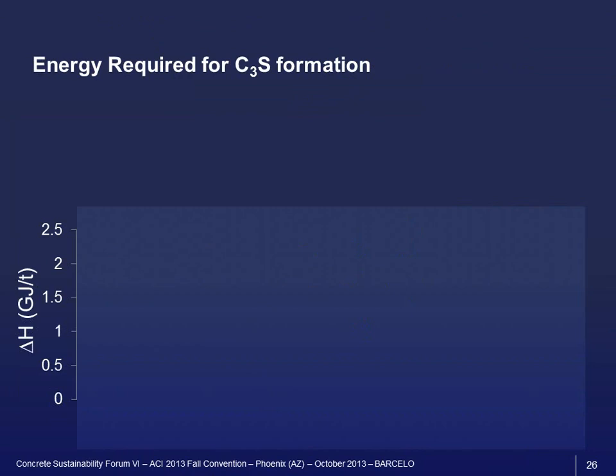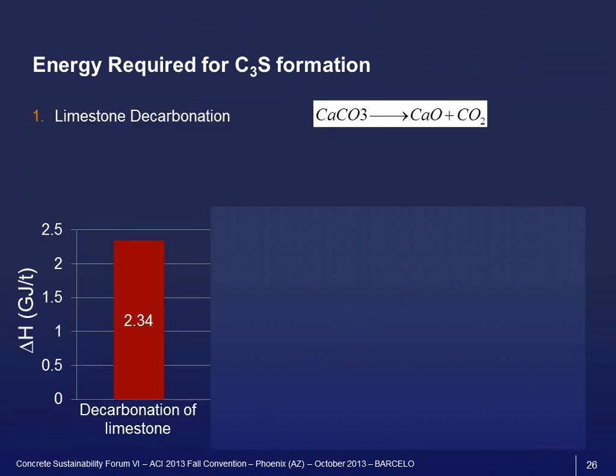What I try to do first is to explain what happens in the kiln CO2-wise and energy-wise when we want to produce C3S. That is the main component of modern cements. So the first reaction that happens in the kiln is the decarbonation of limestone. CaCO3 becomes CaO plus CO2, and here we have the release of the CO2 from the limestone. And in order to drive this reaction, we need a massive amount of energy, which translates into fuels that we need to burn in order for that reaction to happen.